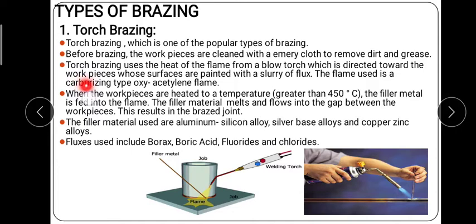The flame used is a carburizing type, that is, an oxy-acetylene flame. When the workpiece is heated to a temperature greater than 450 degrees Celsius, the filler material we are using is fed into this flame, and the filler metal melts and flows into the gap between the workpieces. Whatever gap is there between the workpieces, the filler material melts and flows into it, which you have to join. This results in a brazed joint.